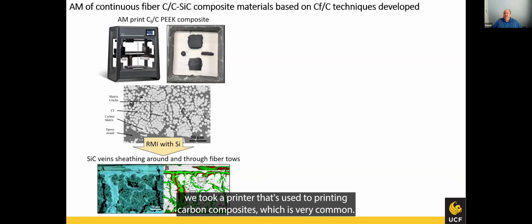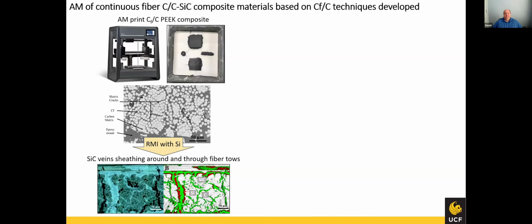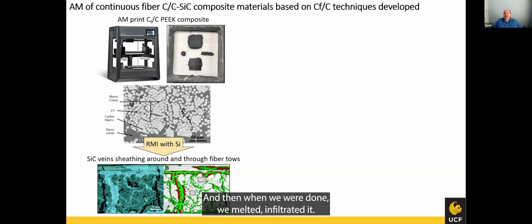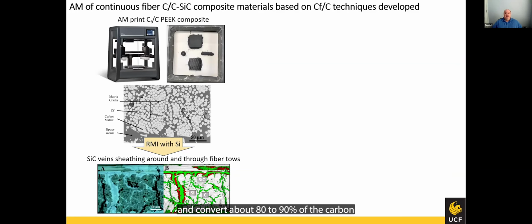So what we did is we took a printer that's used to printing carbon composites, which is very common. And we used the same matrix, which was PEEK. And so they were able to print that, but they printed it with carbon fibers, and when we were done, we melt infiltrated it. So we took the carbon that is in the matrix and we put it in contact with a silicon powder source and we melted. And in that way, the silicon will wick into the microstructure and convert about 80 to 90% of the carbon in the matrix to silicon carbide.